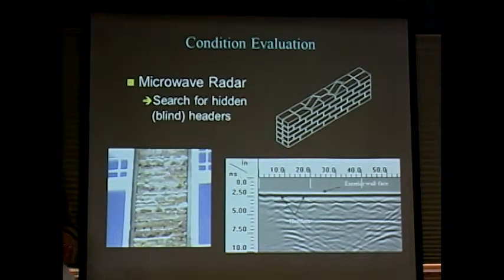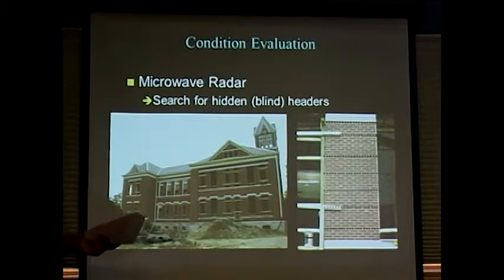They're not always where they need to be, and in this case, using radar, we were really successful at locating exactly where these header courses were, and you can kind of see them sticking out of the backup wythe. We found them to be typically 6 to 10 courses apart at the piers between windows, and that was great. I think that was adequate.